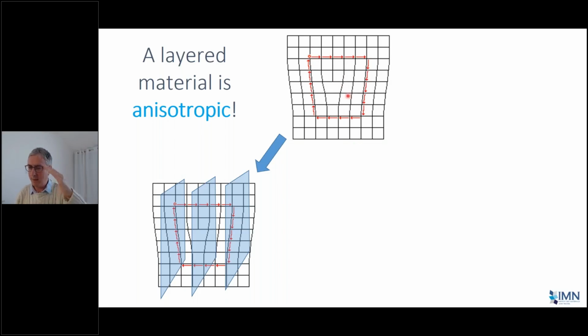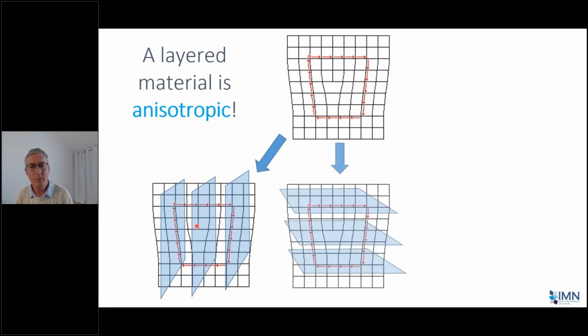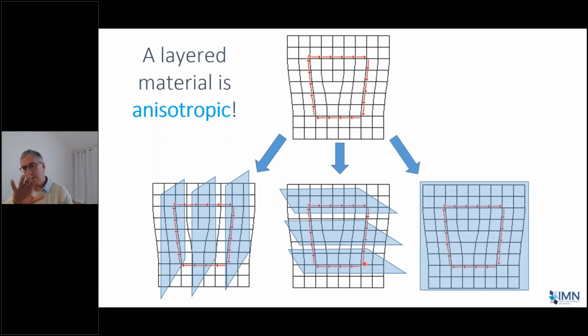We've got 3 directions in the graphite crystal. So this is just, we're talking about an additional layer or an initial row of carbon atoms inserted into the lattice. And we could insert it this direction, but we could also, for example, insert it this direction. So this is the extra inserted material, but the graphite sheets themselves are perpendicular to that. And this is a totally different type of dislocation, because now we're inserting extra material into these graphene planes and not into this plane.